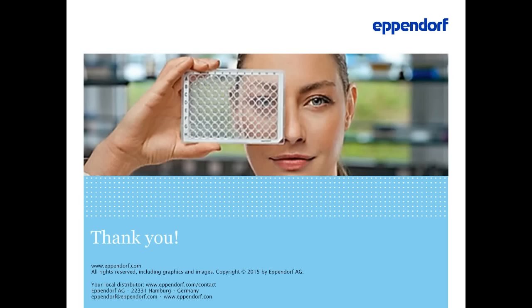Well, the leaching process is strongly dependent on experimental conditions. And leachables are basically all of the organic substances which might come into the solution, might come into the sample under certain laboratory conditions. I understand this question in this way: Eppendorf provides consumables without critical leachables. We do not use any critical additives, and we certify the absence of these critical additives. However, there are some organic compounds which get out of our consumables, and you could see this using very sensitive methods like HPLC or similar. It is not possible to produce polypropylene or any other plastic consumable without any organic leachables coming into the sample. So it's virtually not possible. We don't have critical leachables. We might have some other compounds which are not very critical.